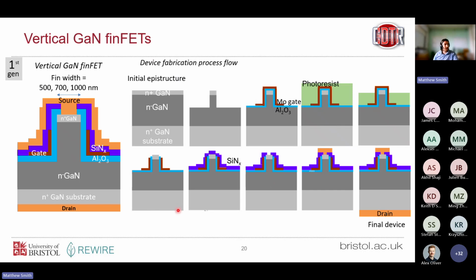So, how do we actually make these vertical GaN devices in Bristol? Well, we start with our GaN-on-GaN epitaxial structure. This is work by my student Chengji Zhang. During his PhD, he's writing up at the moment, his task was to develop a process for these devices based on previous work by Thomas Palacios and Yuhao Zhang at MIT. Based on their papers, we developed this process where we start with this GaN-on-GaN material, working with Dynex Semiconductors here, and make the fin, deposit our dielectric, deposit our gates, and do this photoresist etch-back process, which is very challenging.